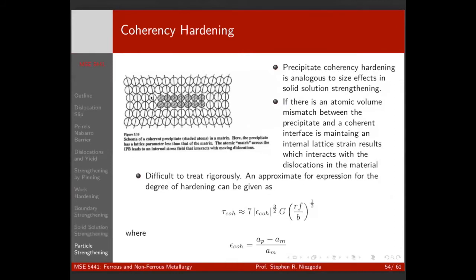Okay? So we have a couple different effects that come about, right? We have coherency, which is basically what I just said. So you have the interface, we have strain, there's an elastic strain field. Coherent interfaces tend to have a higher strain field. We go through this in the reading. The main thing I want you to take away from this is not how these equations look, right? Just knowing what the effects are and being able to say, oh, that's a small particle with a coherent interface. It's not going to be too hard to cut, right?